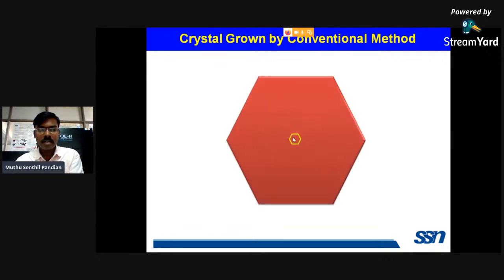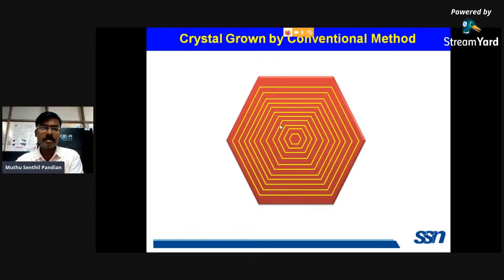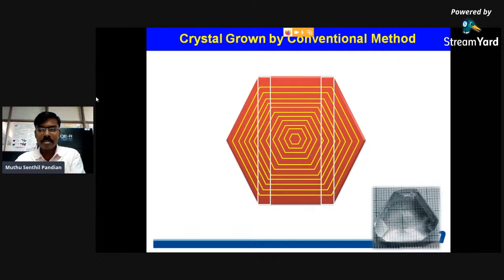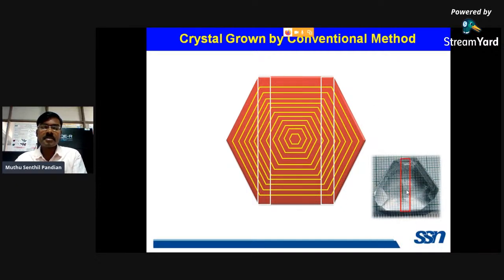A crystal grown by the conventional method will be like this. The nucleation will start like this, with angstrom, nanometer, millimeter and centimeter sizes. The crystal will be grown like this with different morphology. If this is a SHG element, it can be useful for practical device application only in limited ways. The uniformity of the conventionally grown crystal is very low, because you can see: this is the growth in a day, in a 2-day time, in 3 days, a week, a month, 2 months. So with different growth periods, there is no uniformity in the conventional method grown crystals.